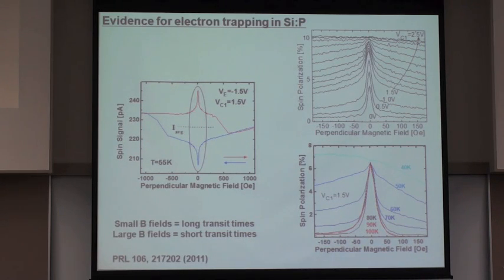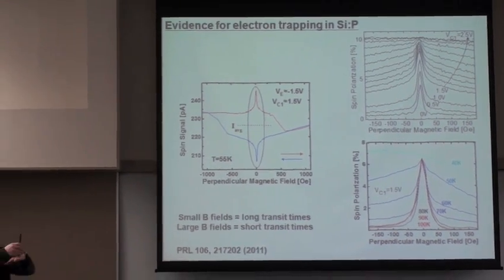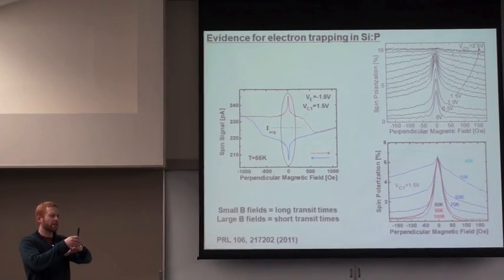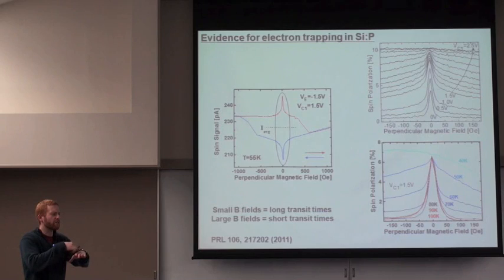It has now two magnetic field scales. It has a very large magnetic field scale. You can see here that at relatively large magnetic fields, we maintain a large spin polarization. Maybe I should explain this a little bit more. Essentially, what's happening here is that as we're applying our perpendicular magnetic field and sweeping it in the red from left to right and in blue from right to left, eventually, and you can see this happens at around 700 Gauss, a very small unintentional misalignment of the device normal with the application of a magnetic field causes a magnetization reversal that lies in the plane.